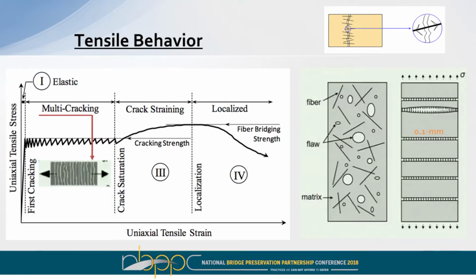So what has been shown through various testing is if I put 1 inch of cover over a black rebar with this technology, using what we'd consider a standard UHPC, I can guarantee 50 years of service life before I start to see any corrosion of that steel. Now, if I used what we call enhanced UHPC, something with even better durability, we can get up to 100 and 150 years without increasing cover. Of course, you could increase cover and get longevity as well, but you can also do it by tweaking the mix design itself. The tension behavior is really unique to this stuff. These fibers in there really create a multi-cracking behavior, and all these cracks are kept to a very fine micro size.